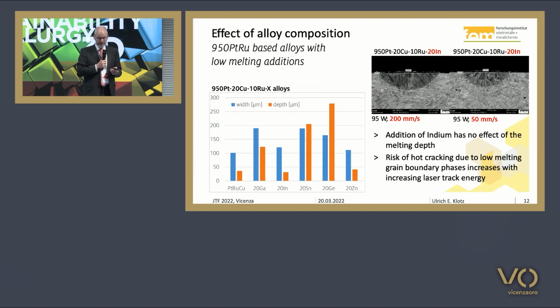Now, if we use some low melting alloy conditions like gallium, indium, tin, germanium, or zinc, we get very different effects. Here we used a series of 950 platinum alloys containing 20 copper and 10 ruthenium, and then the copper was replaced by other alloying elements, or additions were made.